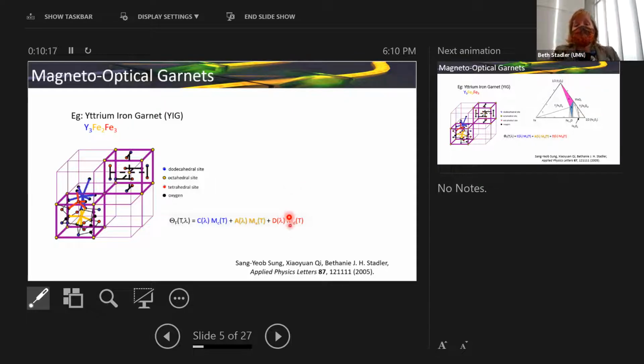So basically you have small, medium, large cations. Actually, half the periodic table can fit into the garnet structure. But you have to balance the ratio of the 3 different sites. So if you have some rare earth element and iron, there's a fair number of rare earth iron garnets that you can form. If you find garnet like as a gemstone in nature, it's probably got more like calcium and aluminum and iron or something in it, but not the rare earth ion.